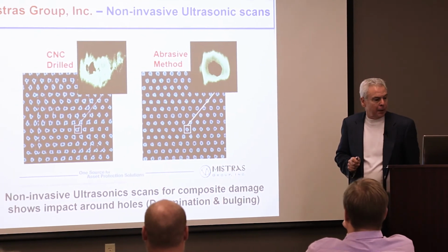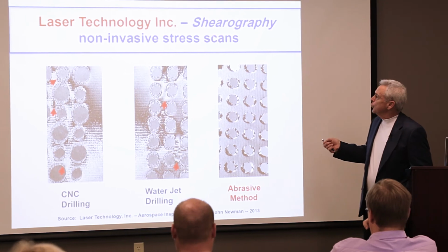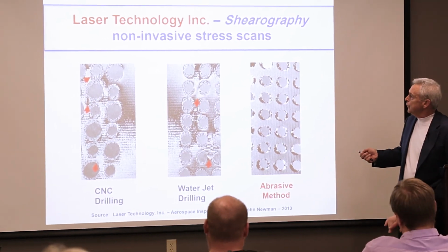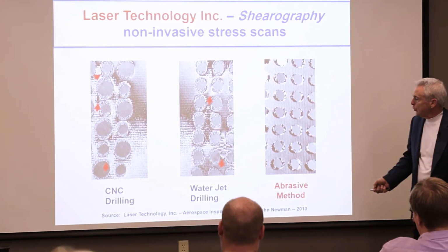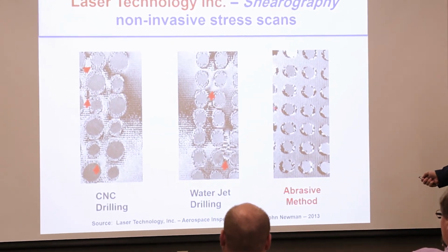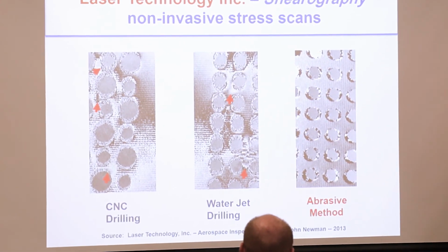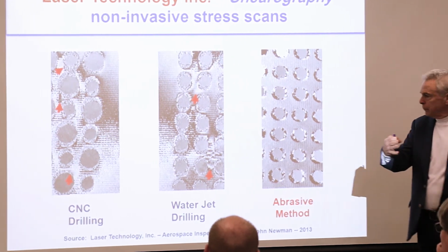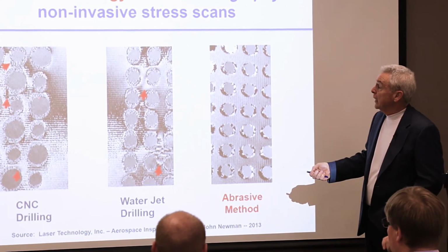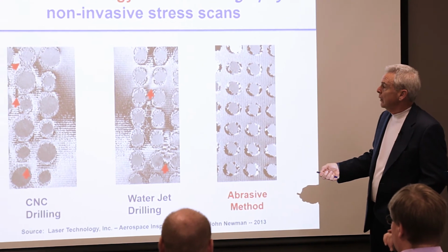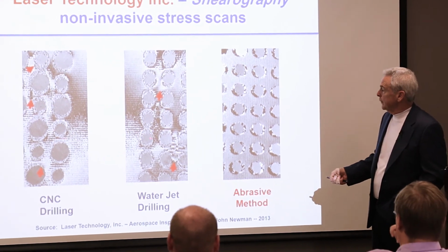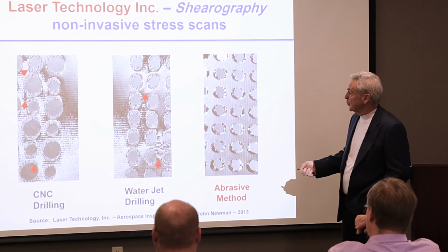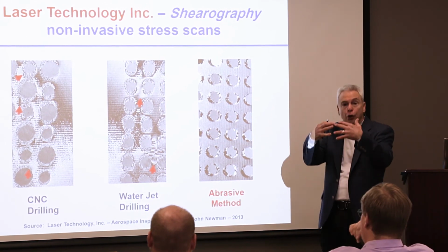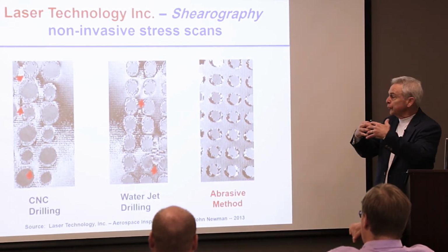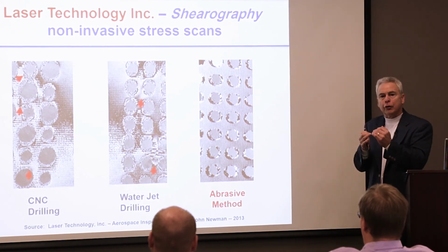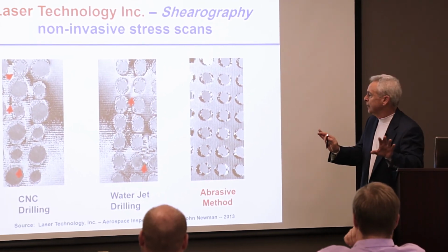Okay. Then we go to the shearography test where they're using, again, the laser to do the non-invasive stress scans. And you can look at CNC drilling, water jet, and the abrasive method, and you can see the same effect. Different testing process, but showing the same effect. And notice how close these get together here when you're looking at CNC drilling and water jet. Actually here they're touching one another, so you've caused a joining between two holes of the stress and the damage internally that you couldn't see if you were looking at the composite.